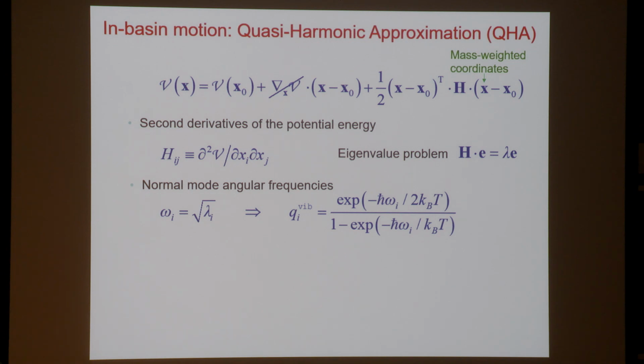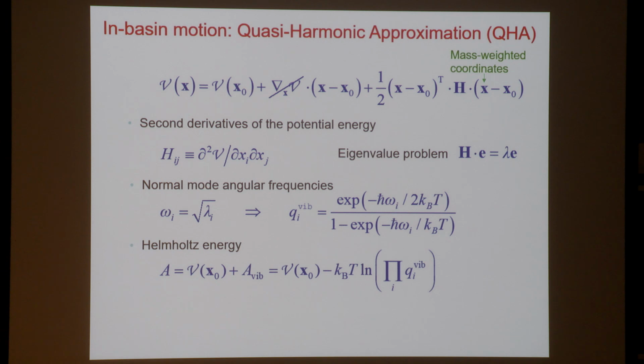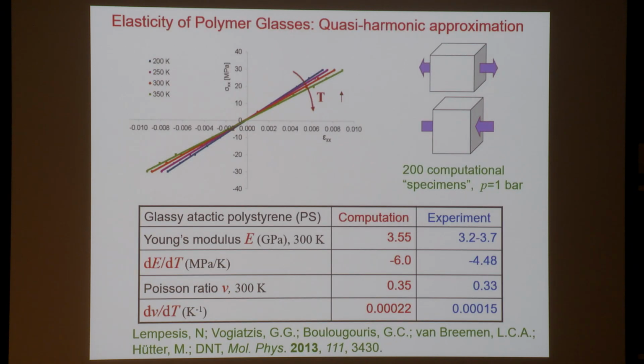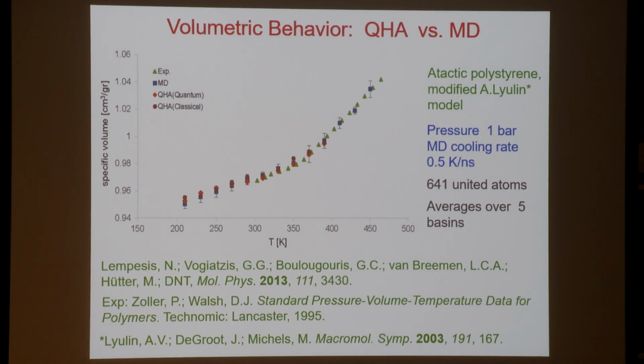So as long as the system is confined in the basin, it can be described by a local thermodynamics, where the Helmholtz energy is the sum of the minimum energy, the inherent structure energy, plus the vibrational contribution due to all these modes. We have a fundamental equation essentially for the system confined to the basin, and we can use it in order to estimate properties. It is important to realize that both the inherent structure energy and the angular frequencies that go into this expression are functions of the spatial extent of the system. If I change the dimensions of the box, they change, and therefore I can learn about the volumetric and elastic properties of the system. So let's look at some volumetric properties first.